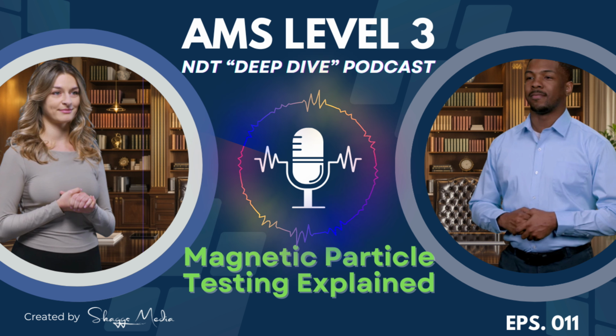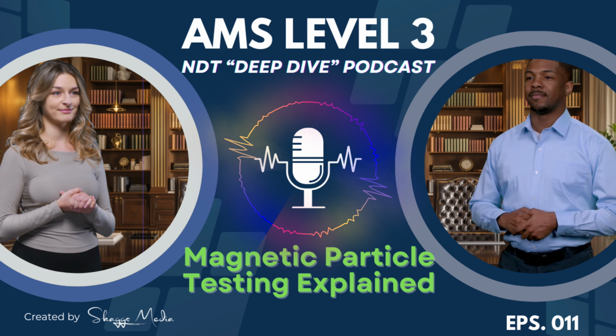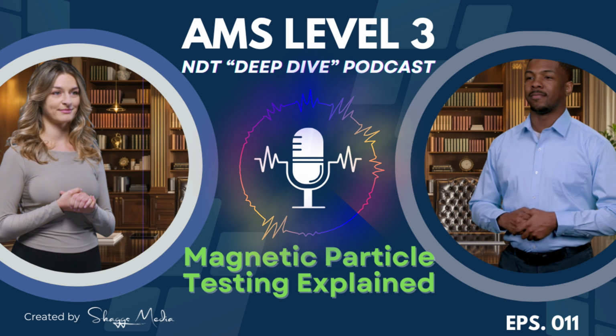Okay. Speaking of setting up the field, let's talk power sources. If our main worry is finding a typical surface fatigue crack, what kind of current immediately comes to mind, and why? For purely surface flaws, definitely alternating current, AC. Because of a phenomenon called the skin effect, it's some electromagnetic thing. AC fields get concentrated right near the surface of the conductor, so it's incredibly effective for finding those really fine hairline fatigue cracks right on the surface. But the downside is it offers very little benefit for flaws that are buried deeper inside the material.